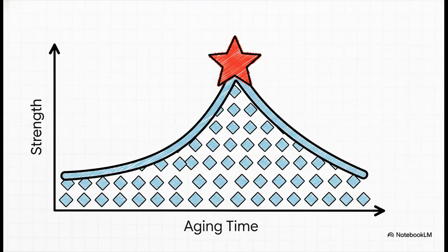And this brings us right back to our T6 temper. The whole point of the T6 process is to stop the aging right at the perfect moment. We call it the peak age state. It's that sweet spot where you have the maximum number of those super effective coherent theta double prime precipitates, just before they start to change into the weaker stuff. It's an incredibly delicate balancing act of time and temperature.